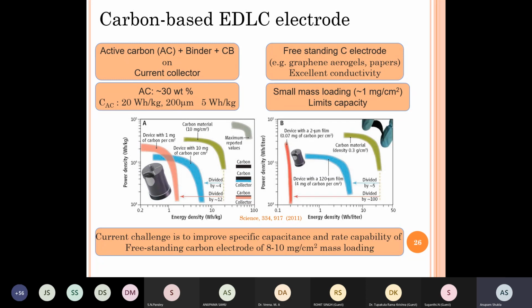So activated carbon plus binder itself is not something that will work as a good electrode. You require a conductivity enhancer, so carbon black is added. Now, even with all of this, it is a particulate structure somehow fixed together. If you have to connect to a circuit, you simply cannot connect directly. Suppose you have an electrode with a geometric area of 10 square centimeters, and you just connect it with a copper wire. It will connect at one point. Let's say it connects with 10,000 particles. For the other particles, the current has to flow through long paths, and the longer the path, the more the resistance. Therefore a current collector is always used. This current collector is usually copper or aluminum. It is tightly pressed with the electrode, and therefore all the particles, or most of the particles, have a direct contact with the current collector.